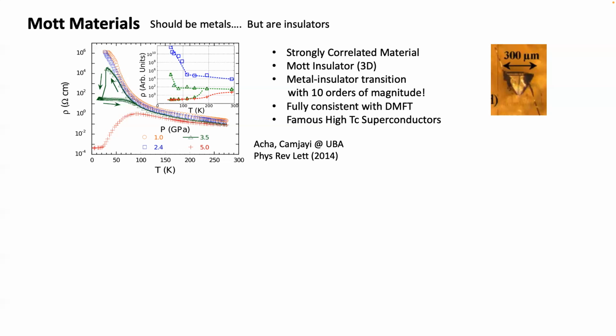But then you apply moderate pressure. This has been done by Carlos Acha in Buenos Aires with samples from Nantes. You apply a moderate amount of pressure, 5 gigapascal, which is very little perturbation for a material, and you see that the resistance collapses by 10 orders of magnitude. Changes of 10 orders of magnitude you only see in astrophysics. So a condensed matter phenomenon that shows this behavior is still amazing to me.